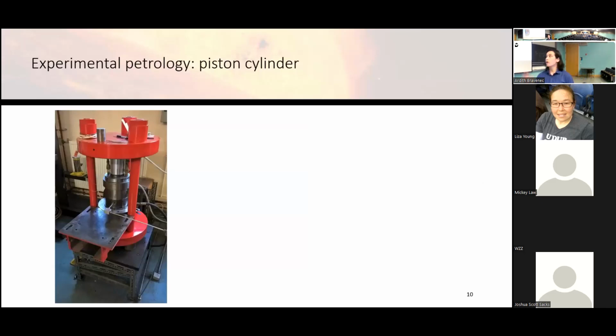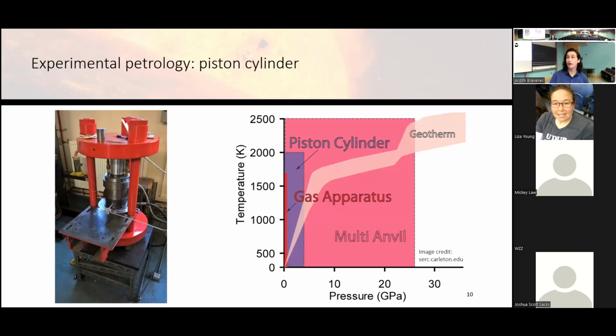Okay, so this is how we actually study these things. This is a piston cylinder press, which is a high pressure, high temperature device capable of reproducing planetary interior temperatures and pressures. So in this case, that means up to about 4-5 gigapascals of pressure and around 1800 degrees Celsius. You can achieve higher pressures and temperatures in a laboratory, but the advantage of the piston cylinder press is also that it's a large volume apparatus, meaning I can get a lot of sample in here. And then that gives me a lot of different opportunities for analyzing those samples.